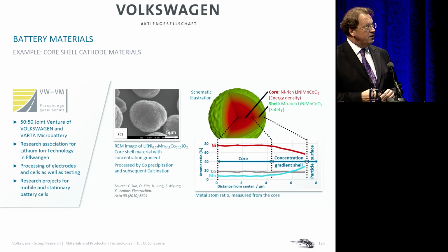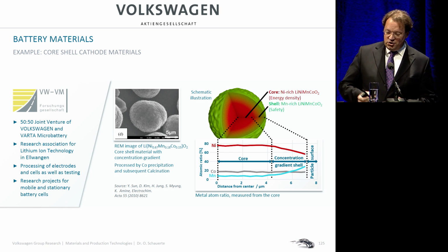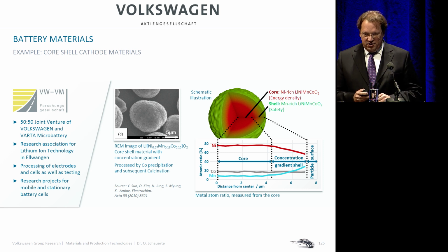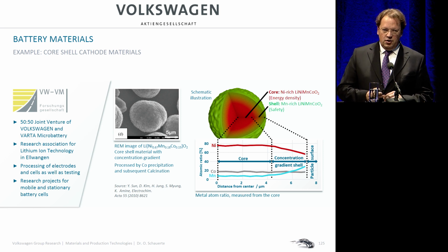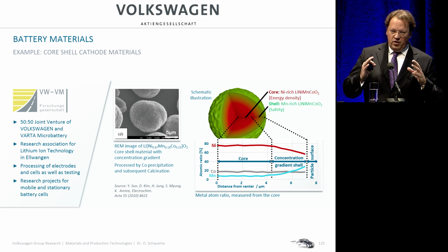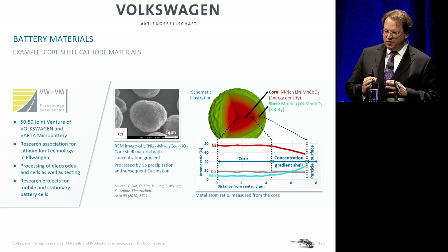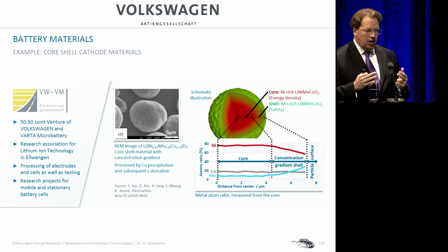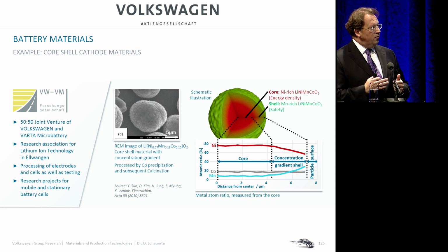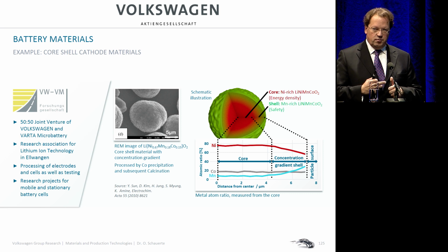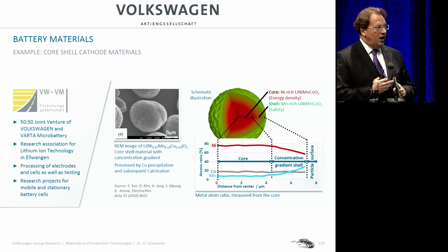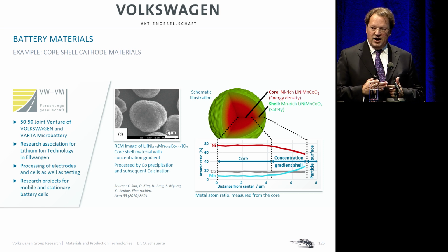And then finally, a view into the future, a little bit more complicated. If you think about lithium-ion batteries, for the cathode we need a powder metallurgical blend consisting of nickel, manganese, and cobalt, or of nickel, aluminum, and cobalt. These powders have to be mixed in a certain way, because the problem is that nickel is, from the electrical point of view, from the charging point of view, the best material. It has the highest loading capacity, but it also has the highest risk to burn.